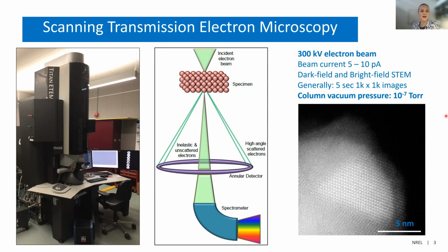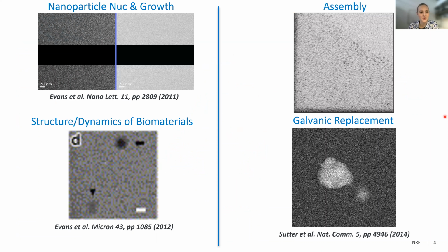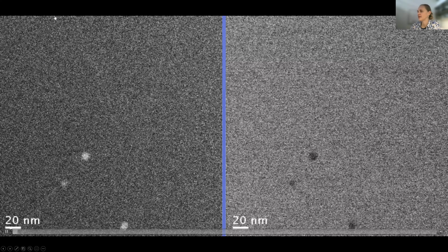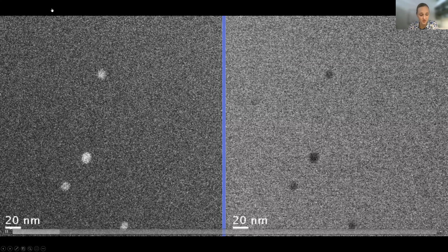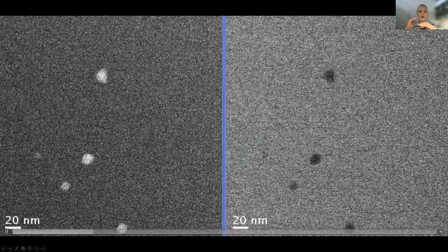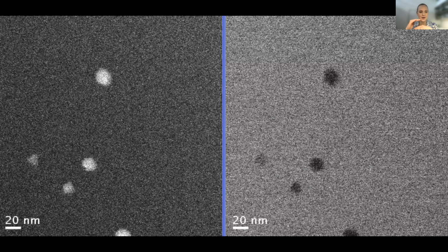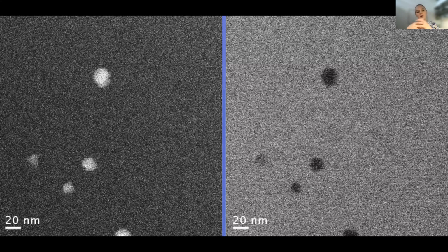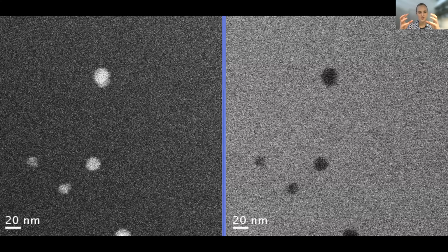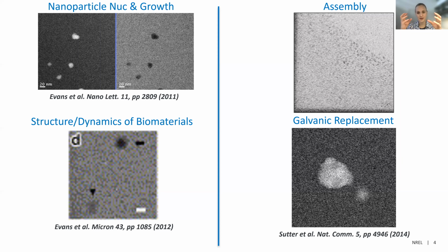Okay, so in my graduate work, I looked at a lot of nanoparticle nucleation and growth. So here's an example of looking at lead sulfide nanoparticles grow under the electron beam. So this is in a liquid cell inside of the TEM, and the imaging electron beam is breaking down the liquid in solution, forming free electrons, which then go and reduce the metal ions in solution and grow these nanoparticles.